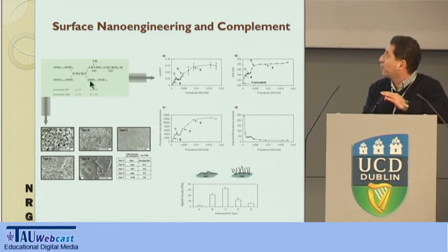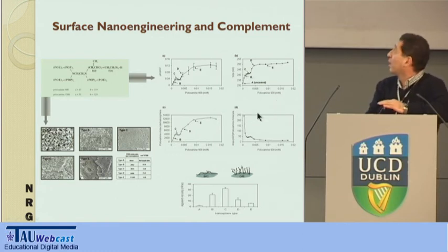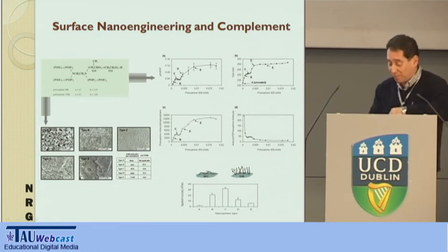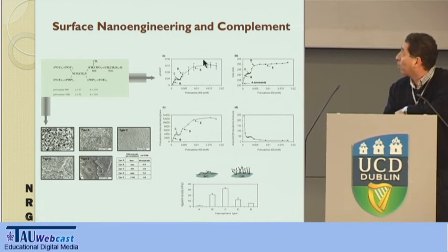So we characterized this. We're basically putting this polymer on the surface. We're measuring an adsorption isotherm, and we are looking into the thickness of the polymer layer by laser light scattering. Then, in terms of the thickness, you can see that you come to a 2 plateau region, around 4 nanometer thickness here and 8 nanometer thickness there. But when you analyze the number of molecules which are sitting on the particle surface, you will see about 3 times more on the top plateau than at the first plateau. And when you do advanced rheology or viscometry, you can actually see the viscosity starts to go up as you're coming towards the first shoulder, and then it starts to drop.